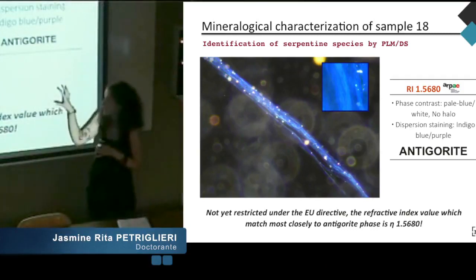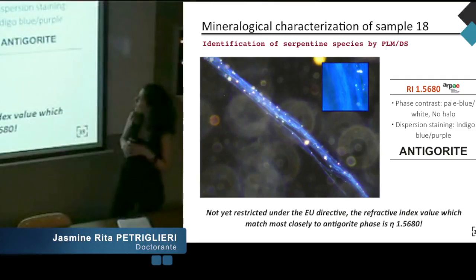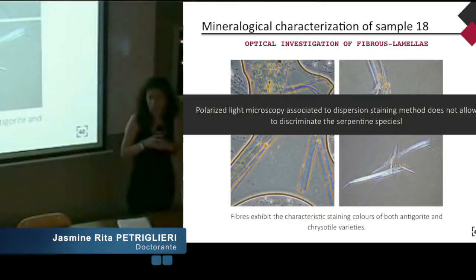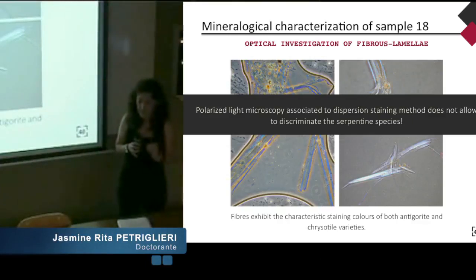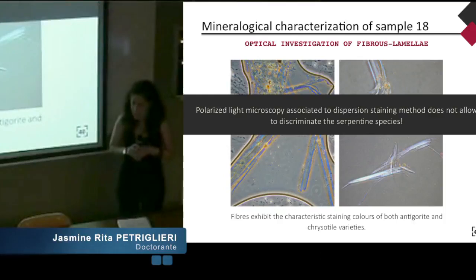We observe a fibrous lamella characterized, in phase contrast mode of observation, by a pale blue to white color, and no halo was observed. Observing the dispersion staining color in dark field, the fibrolamella appears with a beautiful indigo blue color. So we tested these two index values on our sample, and we observed, contrary to every expectation, that fibers exhibit an intermediate behavior and exhibit the characteristic staining color of both antigorite and chrysotile varieties. So this technique does not allow us to discriminate, in this case, the serpentine species.